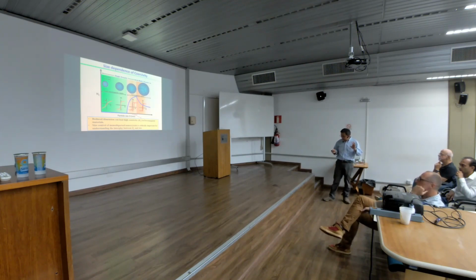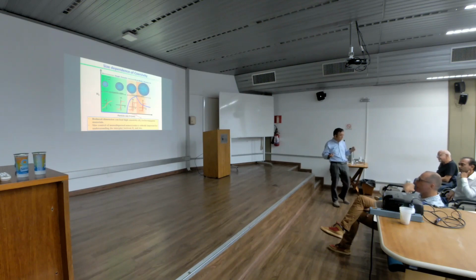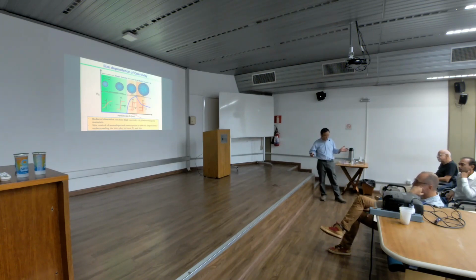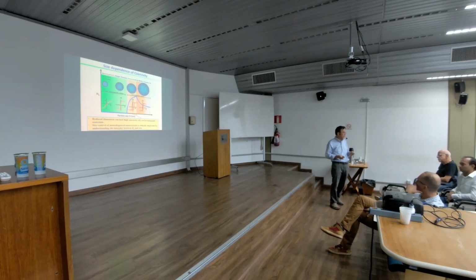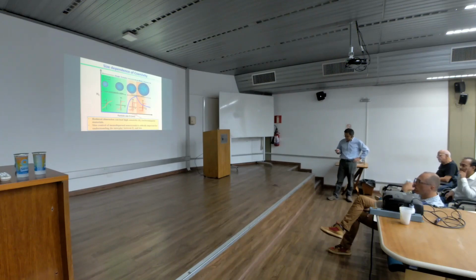And later on, when we were able to make the particle size smaller, we found that to some extent the ferromagnetism, or we call it hysteresis, of the material disappeared. It became like a paramagnetic material. What does it mean? Paramagnetic means you don't have any coercivity. Maybe for soft magnetic material research, they are happy. However, the paramagnetic material is not what we want for many applications. We still need ferromagnetism because the moment is high. So in this case, we try to understand what happens at this point, especially in the case of magnetic recording, if you know that.